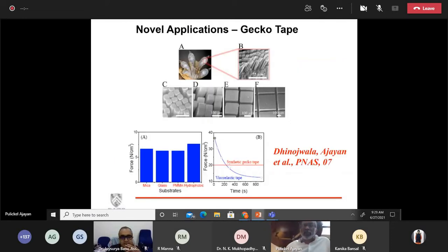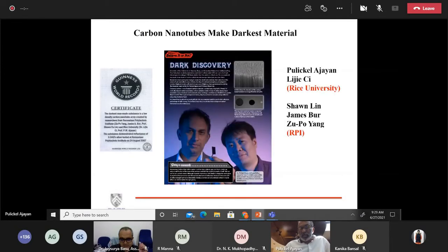That being said, one could think about interesting applications of these structures. One of the things that we looked at was the possibility of using these aligned nanotube architectures as a gecko-like tape, which has strong adhesion using van der Waals forces. And again, there's been a large amount of work done in this area to mimic things like gecko feet with high reversible adhesive properties. And we were one of the earliest to show that this is indeed possible by an aligned array of nanotube structures.